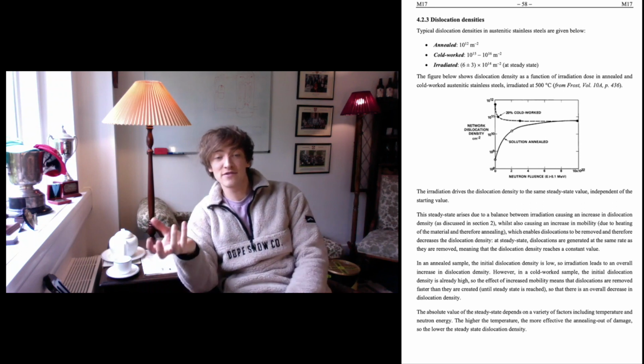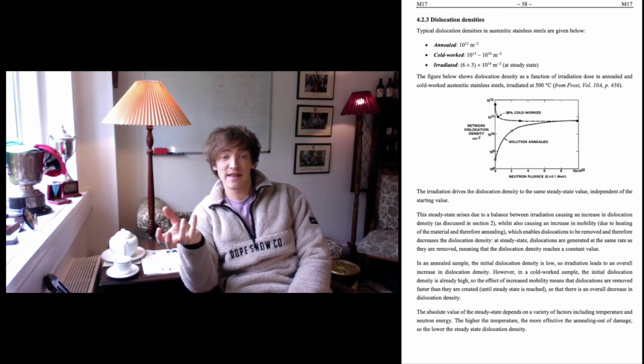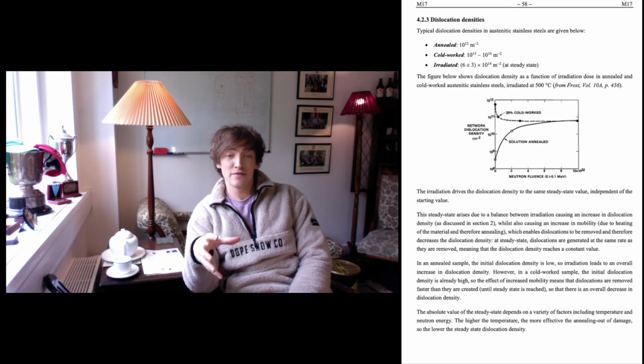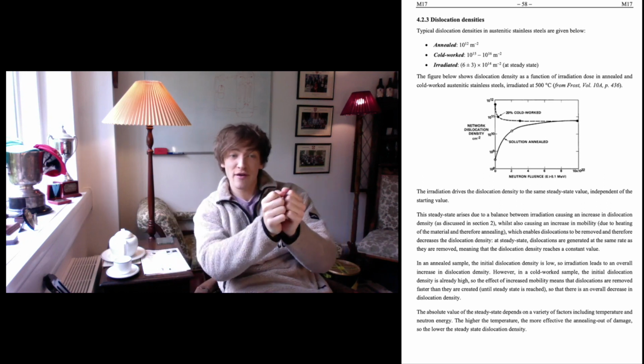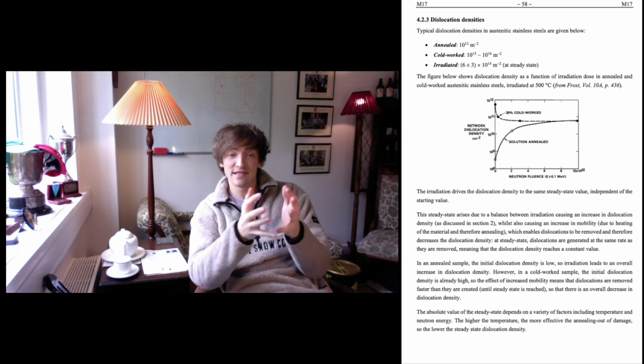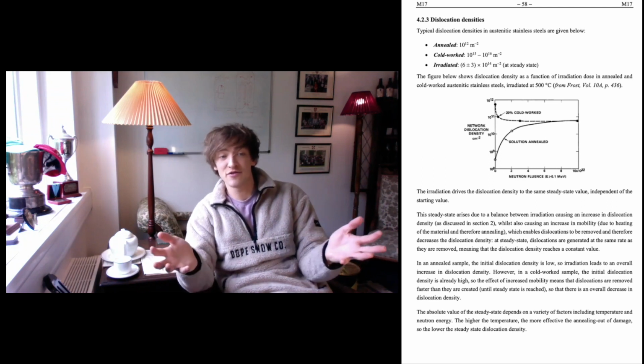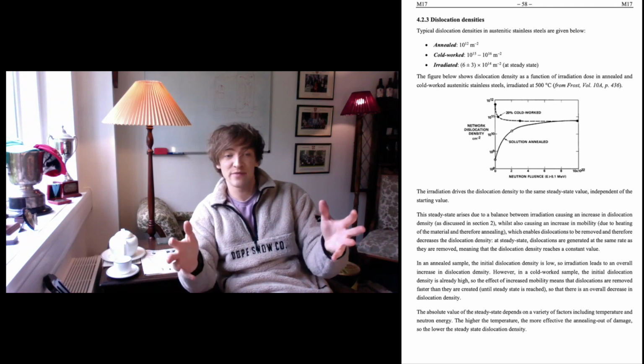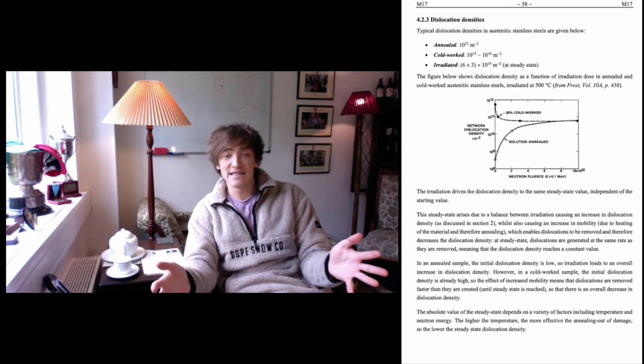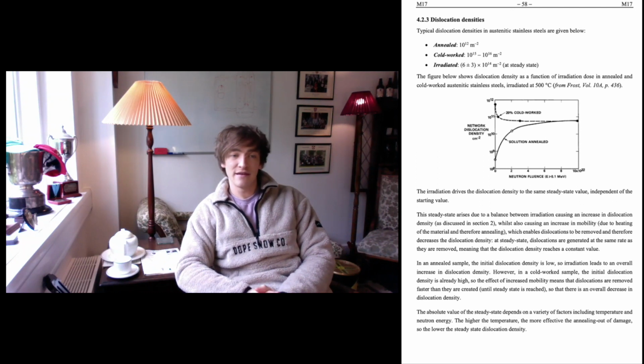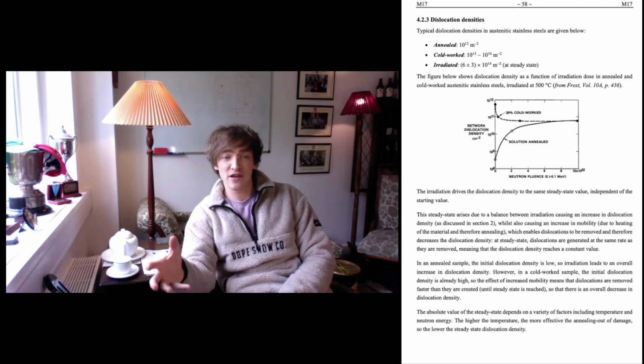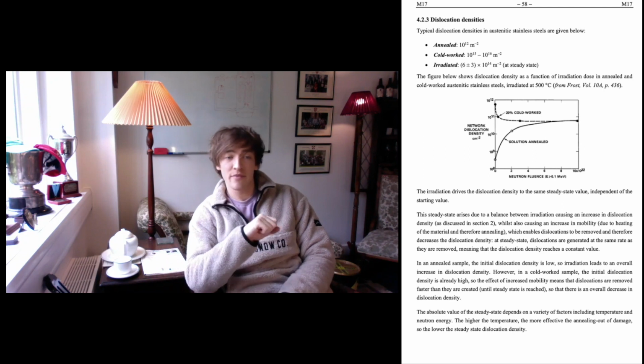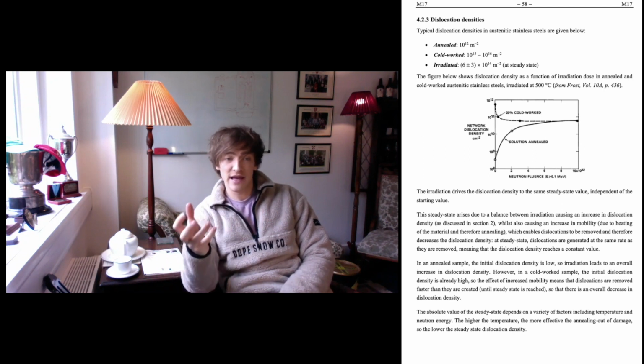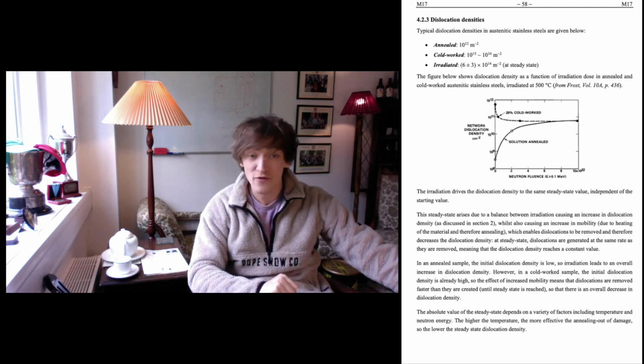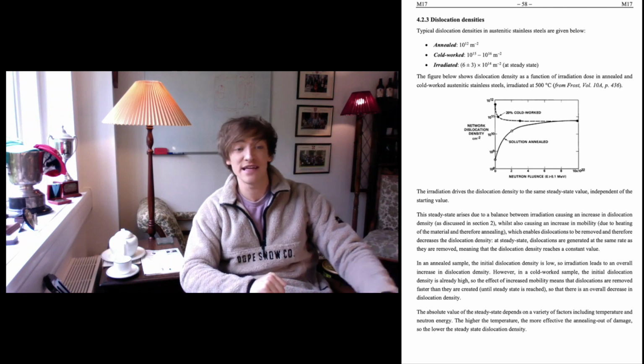And the opposite goes for the annealed samples. They're created faster than they're removed. And eventually, these two battling processes equal each other out, reaching the same steady state value, which itself will depend on the radiation temperature, neutron energy, and several other factors, but that's beyond the scope of the course. The point is, regardless of how you put your material in the first place, if you have a significant enough dose, it will reach the same steady state dislocation density. Okay. So although we've talked about radiation hardening, actually what you can get is radiation softening.